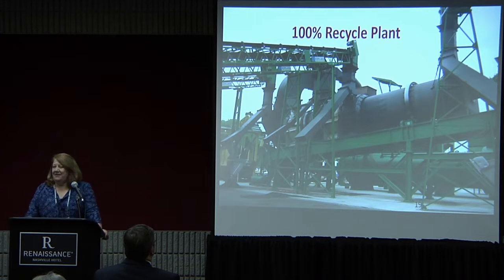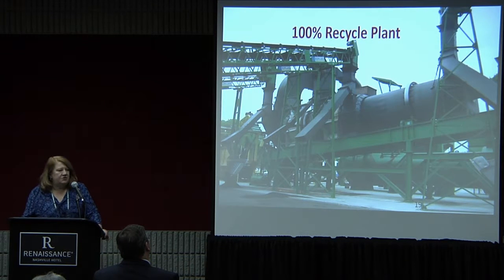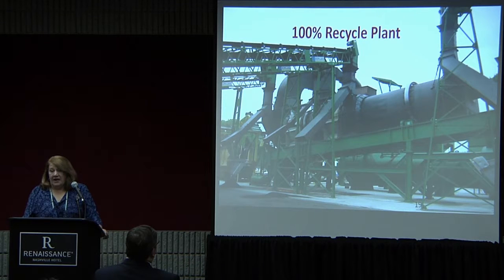But another thing that you could do with thin overlays is use very high percentages of recycled material. This is a plant in Indiana. It can do up to 100% recycled material in this plant. They've got 5 different wrap collars, and they feed different sizes of wrap in at different points in the drum to control the heating. They add a rejuvenator, fairly low percentage, and you essentially have 100% recycled mix, but it's central plant. It's very tightly controlled.